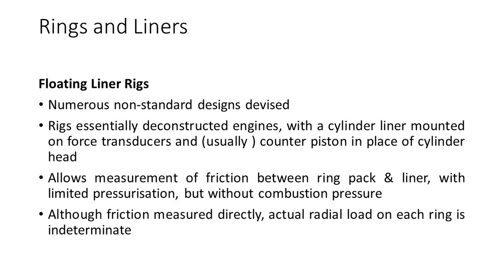Numerous designs of floating liner rig have been devised, a recent example being a unit at the University of Nottingham. The rig is essentially a deconstructed engine with the cylinder liner mounted on force transducers and a counter piston in place of a cylinder head. The arrangement allows measurement of friction between ring pack and liner with a limited degree of pressurisation but without combustion and hence combustion pressure. Although the friction is measured directly, the actual radial load on each ring is indeterminate.